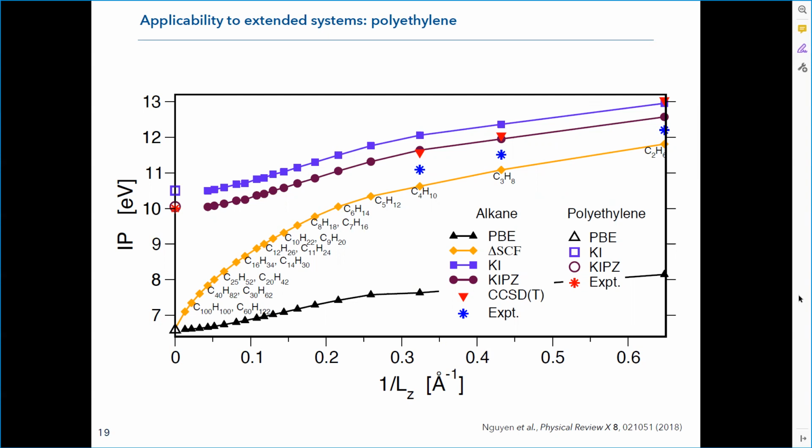But thankfully, thanks to linear response, it is possible to directly calculate this alpha parameter, calculating the derivative of the energy as a function of the occupation of an orbital self-consistently using perturbation theory. You can see that the results we obtain in that case are fairly consistent with delta SCF results that we carried out for increasingly large molecules.